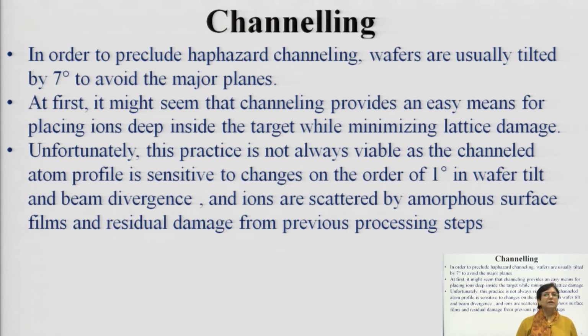At first, it might seem that channeling provides a very easy means for placing ions deep inside. Initially it was found that channeling can give you very deep profiles, but it is not always viable. When you have channeling, there will be minimum damage to the crystal lattice, but you do not want the deeper penetration or deeper junction depths, and therefore channeling is not always favorable. We do not want channeling to happen every time.